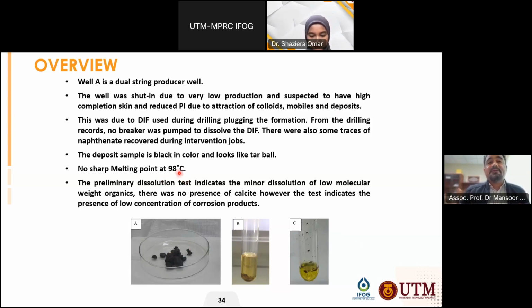This shows that the absence of a sharp melting point could provide useful clues about the nature of the composition of the substance. It could suggest the deposit is a mixture of different compounds, or that it has a complex molecular structure. This might influence how the deposit can be handled or treated in a well stimulation or intervention job. We conducted a preliminary dissolution test that shows minor dissolution of low molecular weight organics.